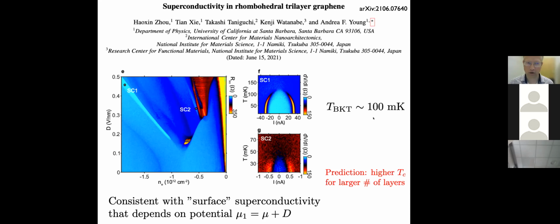The Berezinskii-Kosterlitz-Thouless transition temperature in those systems was 100 millikelvin. But at least we can directly use the previous results to predict that if you go to a larger number of layers, let's say 4 or 5, you would get a much higher TC. And one also finds that these results are consistent with surface superconductivity, where the superconductivity only depends on the potential that is the sum of the average potential plus this d here. I will not go into too much detail, but that's the message.